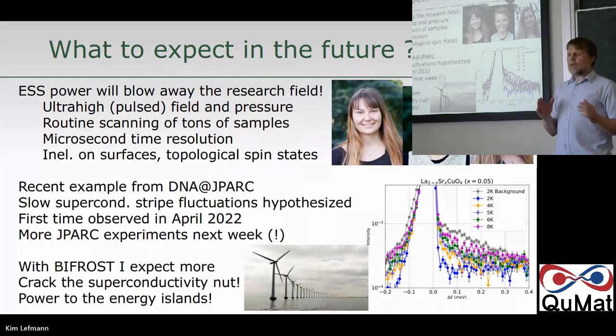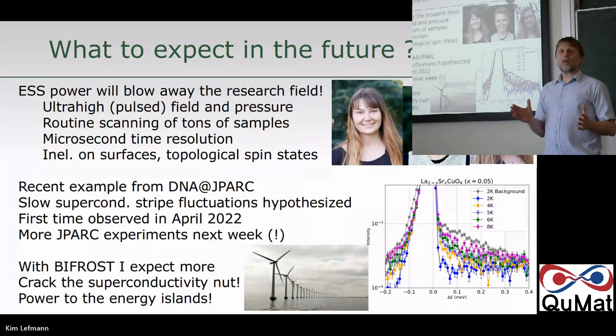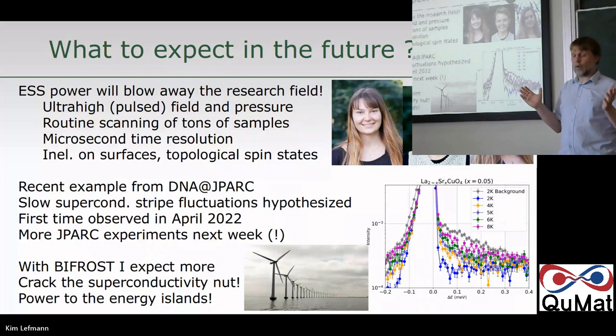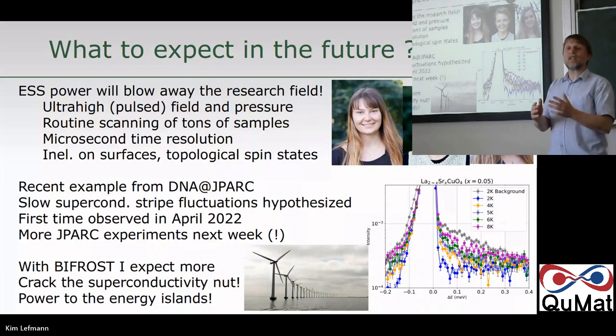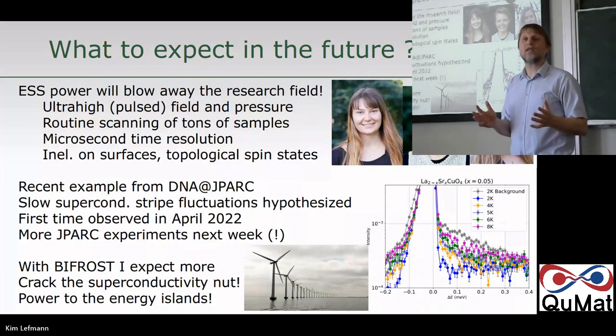Okay, there is a sum rule for magnetic neutron scattering. This is a dynamic correlation function; you sum that up over all Q and energies, and you basically get your number of spins times S times S plus 1. That's it, in suitable units. But we are nowhere near having seen all the magnetism. We can sum up only a quarter of it. There is something hiding in the background that we can't see yet.